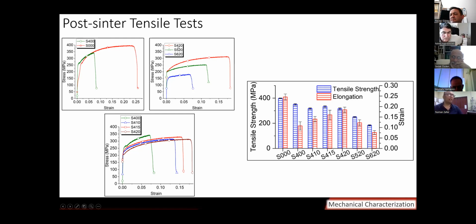Here you can see that again, increasing the core diameter decreases the tensile strength and the strain of the wires, and presence of the iron boride phases increase the strain of the wires, but the overall behavior of the wires, if they have the same core diameter, is almost similar, not very much different from each other. But is it a bad thing or a good thing? It is not a good thing.